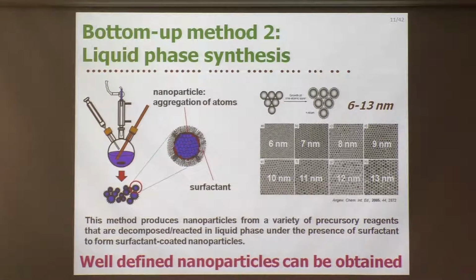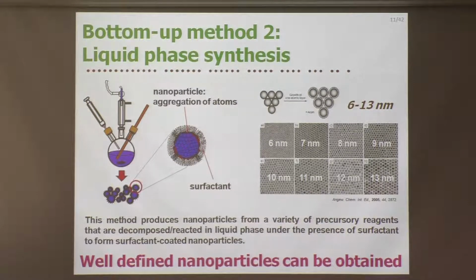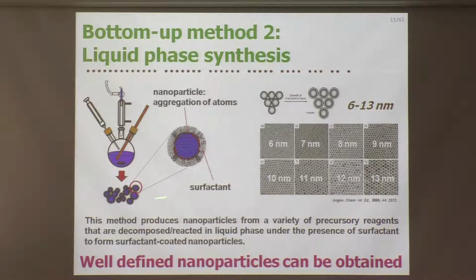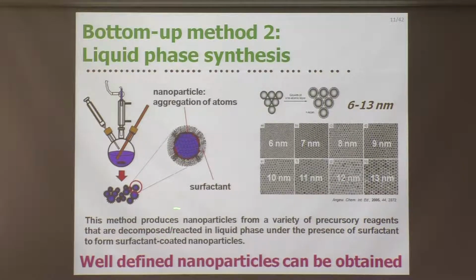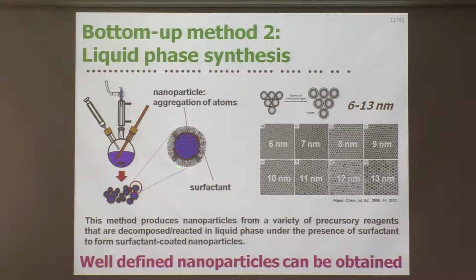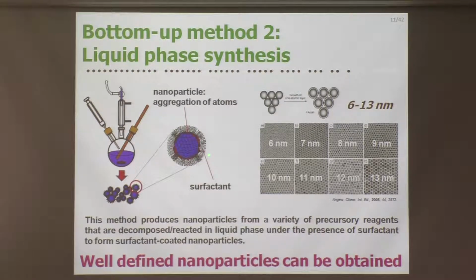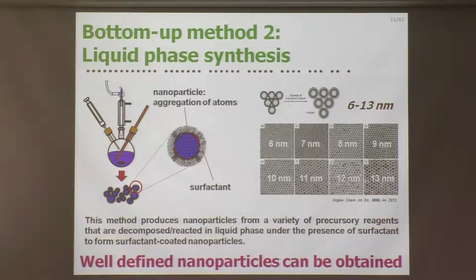Okay. Another example of chemical synthesis is the liquid phase synthesis method. As shown here, this method carries out the reactions in the liquid phase. This method produces nanoparticles using a variety of precursor reagents that are decomposed and reacted in a liquid phase in the presence of a surfactant. So with this method, we can get nanoparticles coated with a surfactant. Because of the presence of the surfactant, they form a well-dispersed state so that the reaction is carried out homogeneously.